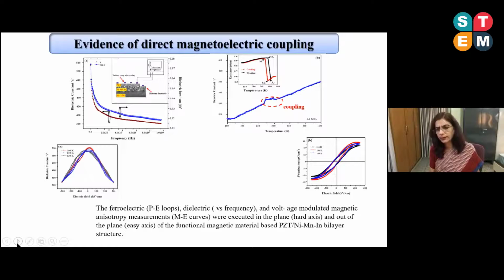As a result of that phase transformation, we believe that voltage has been induced in the adjacent PZT layer, and the strain developed in FSMA gets transferred to the PZT layer, which is responsible for the change in the dielectric constant.